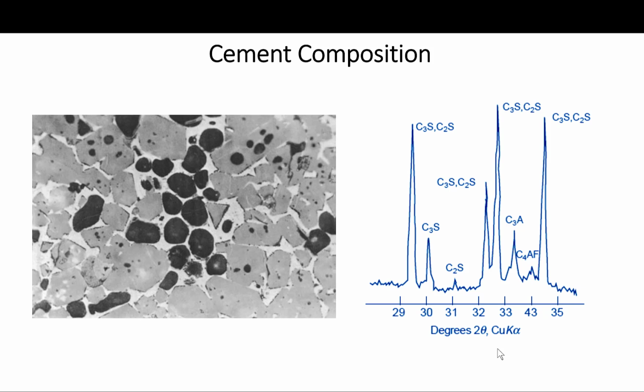By scanning the sample through a range of 2 theta angles, all possible diffraction directions of the lattice should be attained due to the random orientation of this powdered sample or material. Conversion of the diffraction peaks to the D spacings allows identification of the mineral.